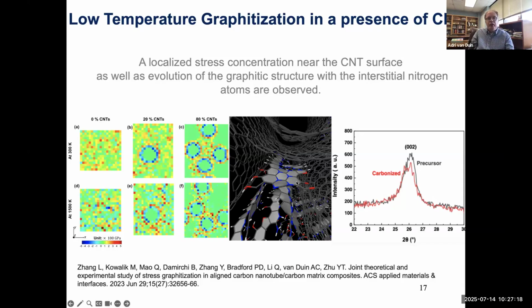So these tools are very useful to check how we can control the carbon fiber growth and what type of additives are going to be efficient in there. And also, importantly, how good quality they need to be. Clearly, carbon nanotubes can be very expensive, but if the size and the chirality of the carbon nanotube doesn't matter that much, then these materials can get much cheaper and become much more credible additives. So we can see how the quality of the carbon nanotube can affect the graphitic growth.